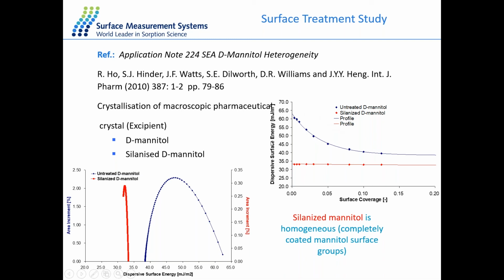We can also see at this region here, the infinite dilution region, we actually have a greater dispersive surface energy for the untreated mannitol. What this is telling us is that at this concentration, we're able to actually access higher energy sites, higher active sites on the surface of our sample. So in this case, we have a higher dispersive surface energy. And these sites are not available in our silanised mannitol. This is giving us an idea of the surface homogeneity or heterogeneity. So the more linear our profile, the more homogeneous, and the more curved our profile, the more heterogeneous.